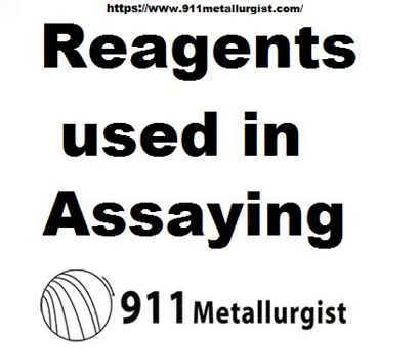Bromine, Br, specific gravity 3.0 — practically pure bromine. It is a heavy, reddish-brown liquid, and very volatile. It boils at 60 degrees centigrade, and consequently must be kept in a cool place. It gives off brown, irritating vapours, which render its use very objectionable. Generally, it answers the same purpose as aqua regia, and is employed where the addition of nitric acid has to be specially avoided. It is also used for dissolving metals only from ores which contain metallic oxides not desired in the solution.